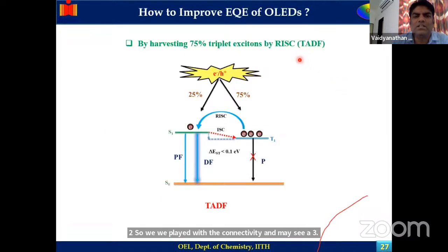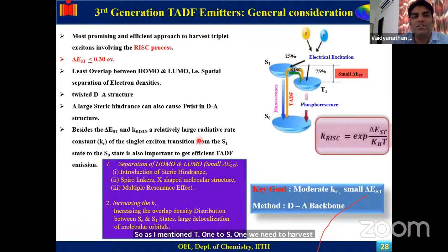So next one is reverse intersystem crossing, TADF material. So as I mentioned, T1 to S1, we need to harvest the energy. In this concept, TADF is the most promising and efficient approach to harvest the triplet exciton, which involves the reverse intersystem crossing process. And the S1-T1 gap is supposed to be less than 0.3 electron volt. That means the value is supposed to be very close. So it can be 0.003, which will be very, very good for you. Okay. So this can be achieved.